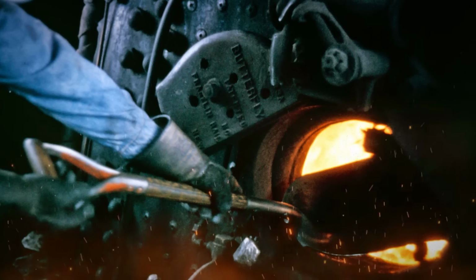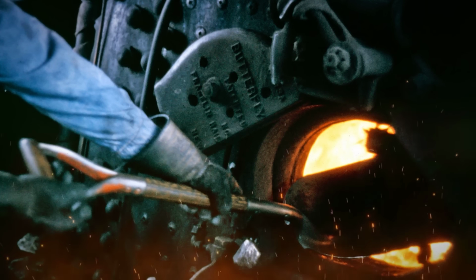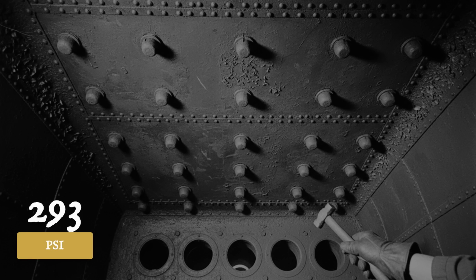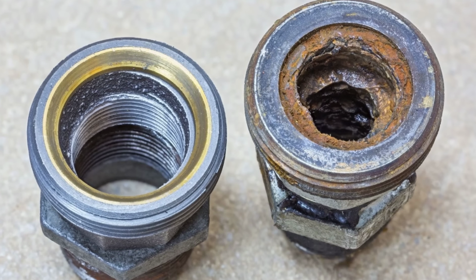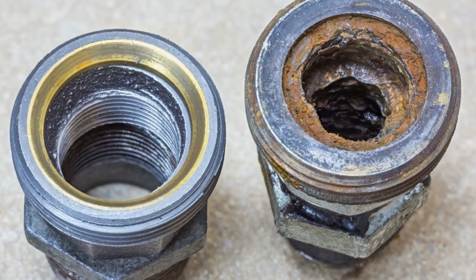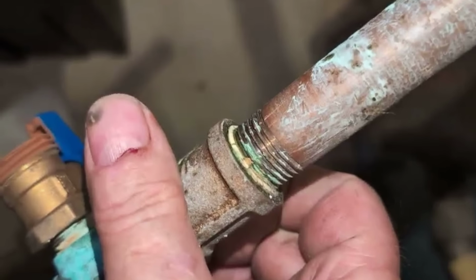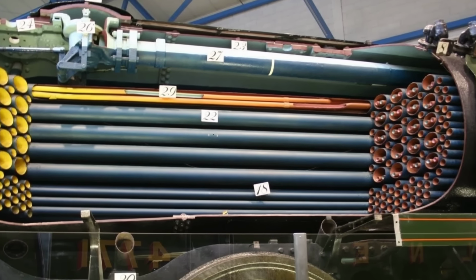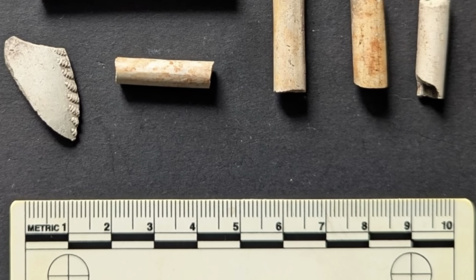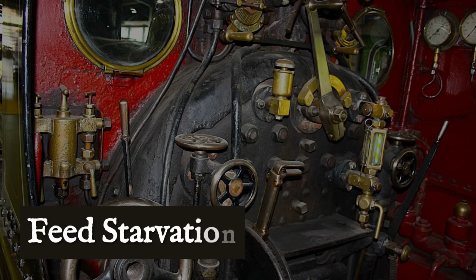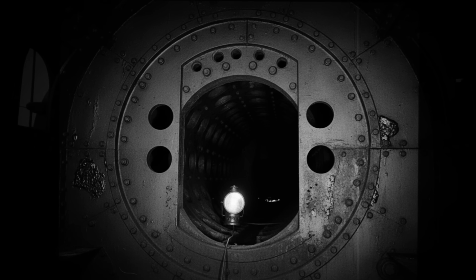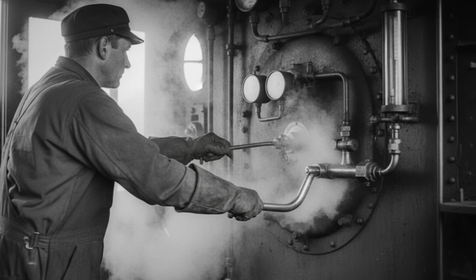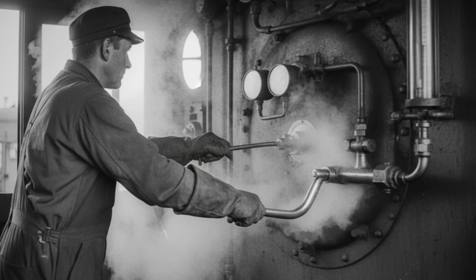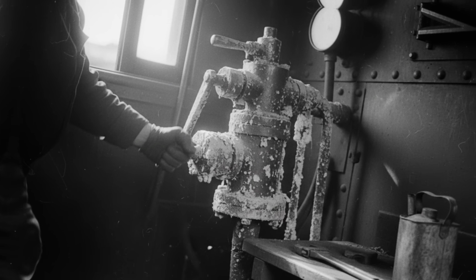With the firebox roaring at 2,000 degrees, water stops reaching the boiler. The crown sheet, still under 300 PSI, is left uncooled. Calcite deposits, invisible until too late, choke the half-inch brass feeder pipes. What should be a clear passage for makeup water becomes a stone-cold plug. The sight glass may still read safe, but the boiler is running dry. The engineer pulls the lever and hears only a hiss. The injector, fouled by a decade of hard water, cannot overcome the pressure.